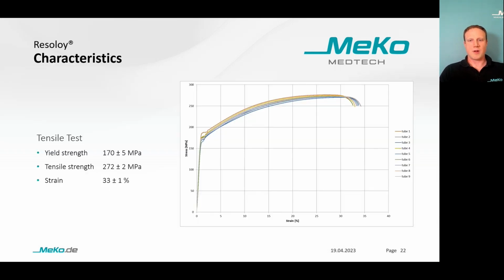You can see here on the right side 9 stress strain curves of one exemplary tube batch of 1.8 millimeter tubes with a wall thickness of 160 microns. And as you can see, there's hardly any deviation in the results. The yield strength of Resoloy in the tube state is about 170 megapascal. The tensile strength is about 270 megapascal, and the strain is around 33%.